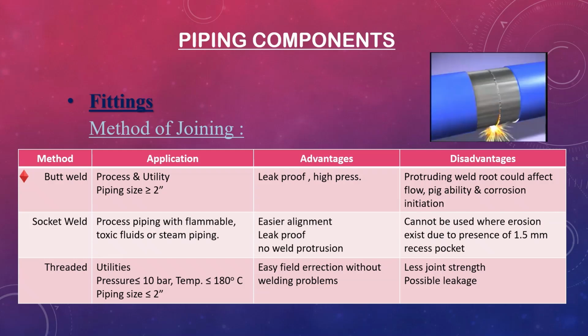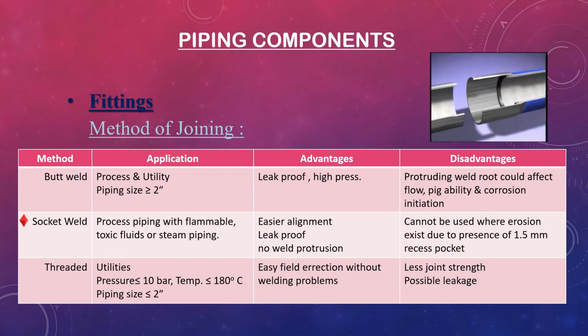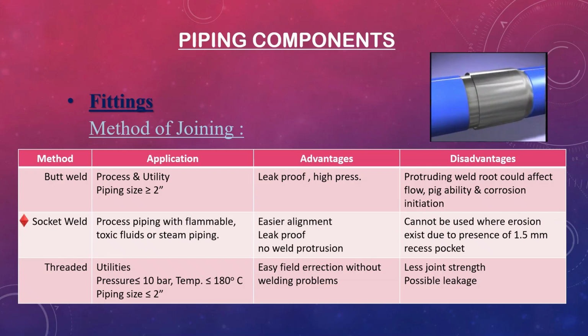So if butt weld is for big, high-pressure, high-flow applications, the socket weld seems tailored for smaller, equally critical lines. Socket weld fittings are designed for process piping under 2 inches that carry flammable, toxic fluids or high-pressure steam. Their pros are clear. They offer easier alignment and faster assembly than butt welds, they are leak-proof, and they avoid that problematic internal weld root protrusion. But the drawback here is startlingly specific, hinging on a microscopic distance. It's incredible. Socket welds cannot be used where erosion is a concern, and that's due to the mandated presence of a 1.5 millimeter recessed pocket between the pipe end and the fitting wall. Wow.